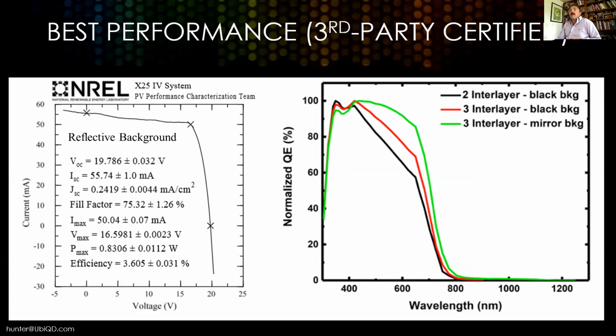Putting it all together with all of our different advancements and innovations, we've been able to achieve a record efficiency for luminescent solar concentrators that was certified by a third party, specifically at the National Renewable Energy Laboratory. You can see the data here. The record champion that we got certified was around 3.5%, which is about 35 watts per square meter in direct sunlight.